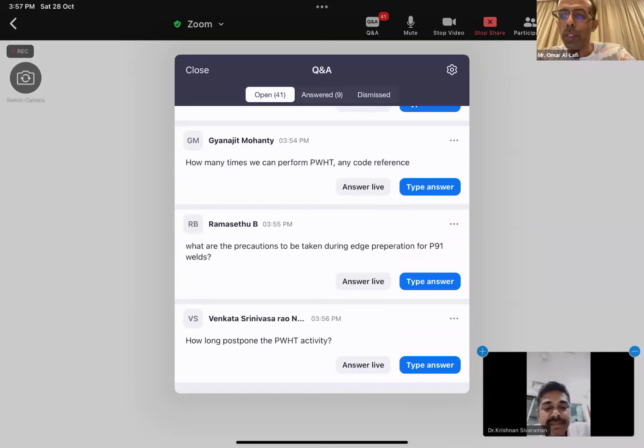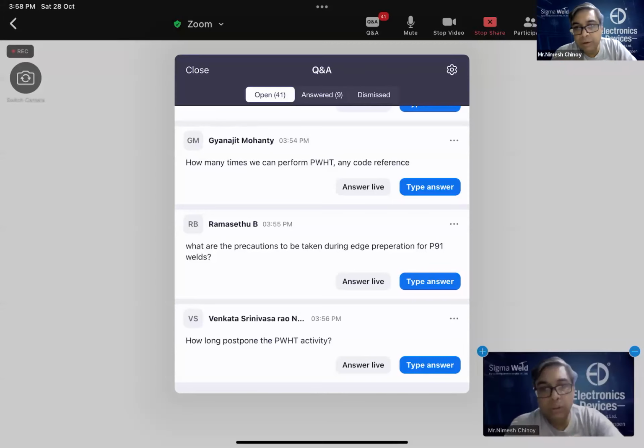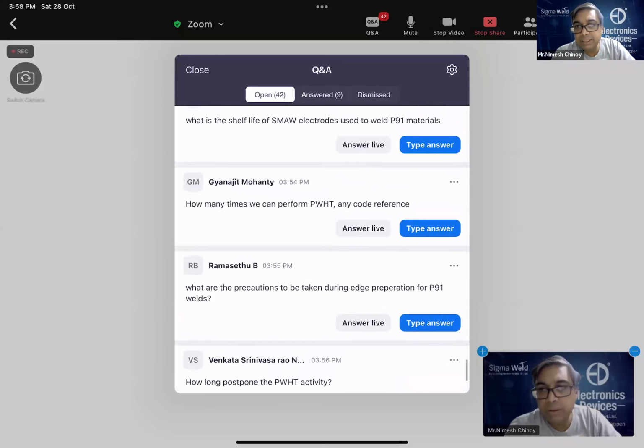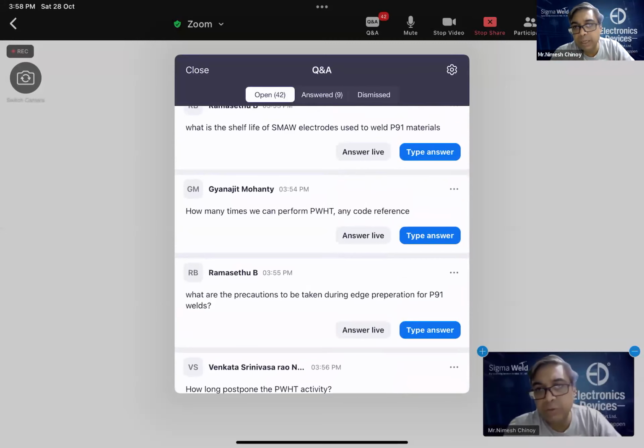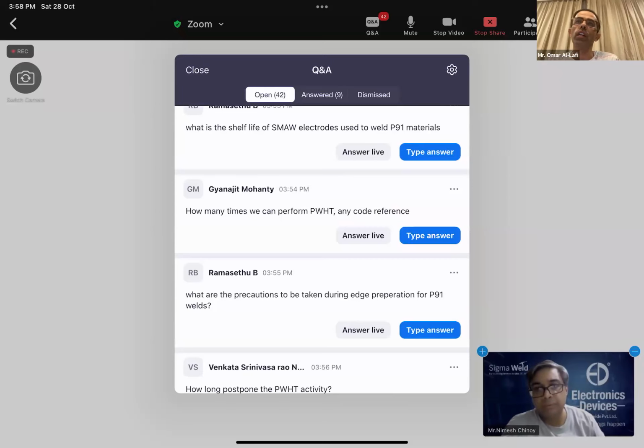How long can we postpone the PWHT activity? There should be no delay, for reasons we mentioned earlier, that the delay can result in stress corrosion cracking due to moisture or sulfur species. The only way around it is if you did post heat or DHT, and then you could redo the PWHT. If you took it up to 400, you could pause, but it cannot be for very long. Yes, it'll be brittle. We should not forget that the hardness is very high in the as-welded condition. Correct. And it is prone to cracking.